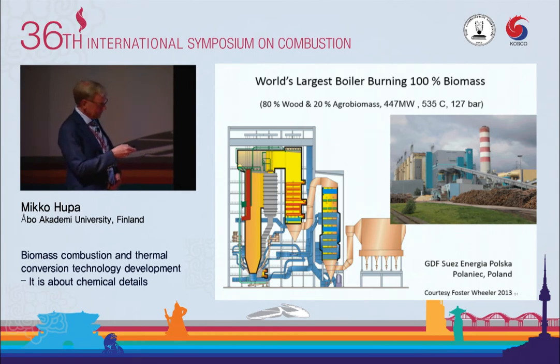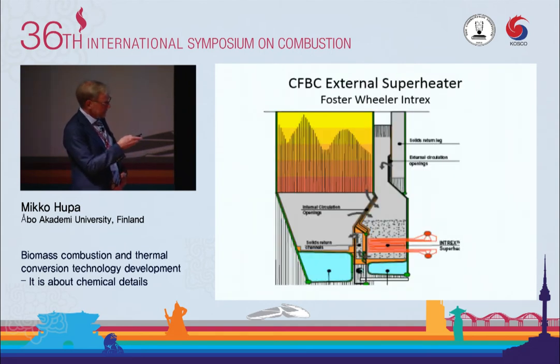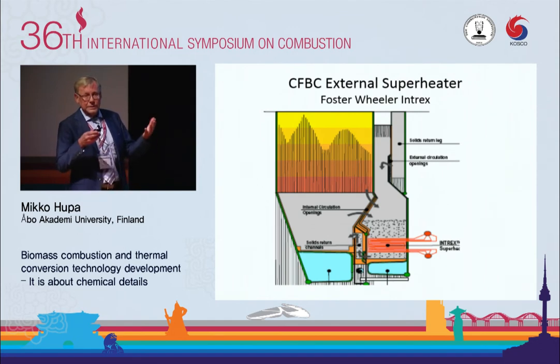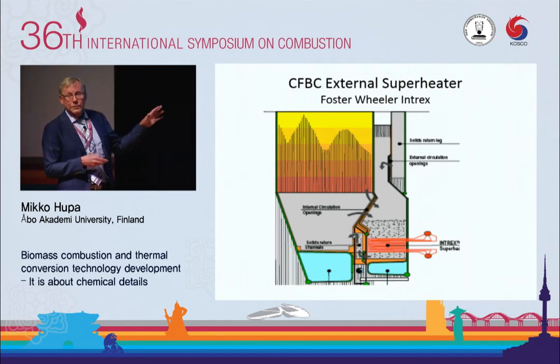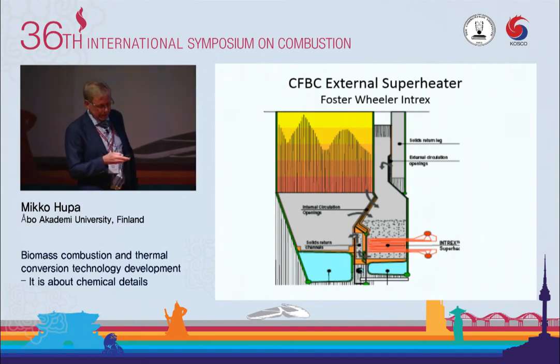One solution they have, which is interesting, this is Foster Wheeler in Poland. In a circulating fluidized bed, this is the furnace, the bed material is circulated back, and there is a feeding system of that back to the furnace. That feeding system is also a small bubbling fluidized bed, and they put a heat exchanger, the hottest superheater, in there, and could increase the steam temperature somewhat by the contact with the hot sand without the contact of the flue gases and the chloride. This is one way of showing how things advanced. Anyway,